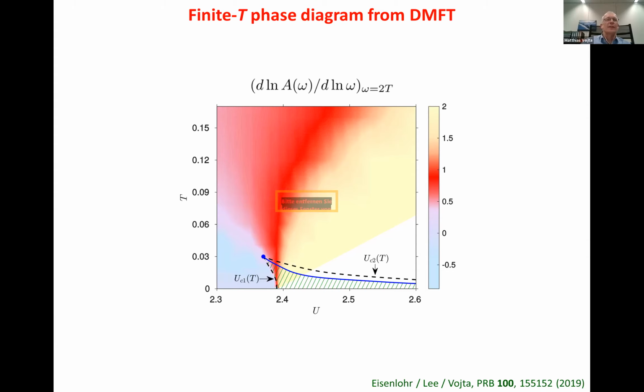You see now, and that's the suggestive thing of this plot, this red regime, which shows where this power law in the phase diagram, this spectral power law, does exist. You see the typical quantum critical fan, bounded by a regime of metallic states in blue and by something insulating in yellow, with this power law stuff in the middle.